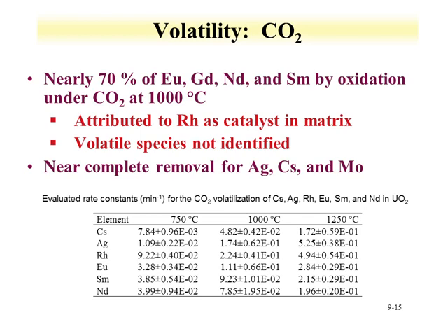Some reactions with additive ligands can drive volatility. An example is with using CO2 under oxidizing conditions. Nearly 70% of the lanthanides can be removed in some experiments by treating oxide fuel under CO2 up to about 1,000 degrees. Some of this work is attributed to the presence of rhodium as a catalyst, a rhodium metal in spent nuclear fuel, driving this. This work is still at a fairly early phase. The volatile species have not been identified.